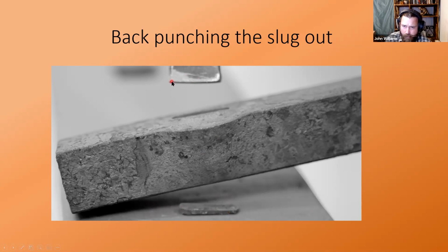The punch, again, is 7/8 by 1/8, so it's only 1/8 of an inch thick. If you try to force an overly large slug out, you're going to force your punch to work a little bit harder. So in general, I try to have my slug thickness by the time I'm done no thicker than whatever the width of my punch is. So in this case, it's an 1/8 inch wide punch, and I don't want to try to clear out any more than 1/8 of an inch. So you're getting pretty close to the bottom when you do this.